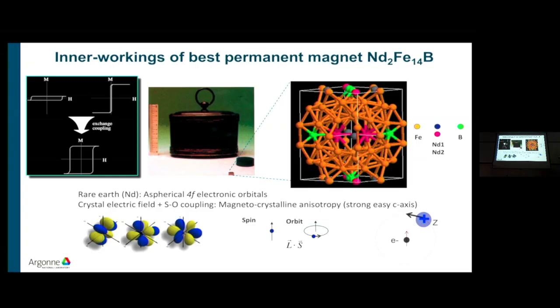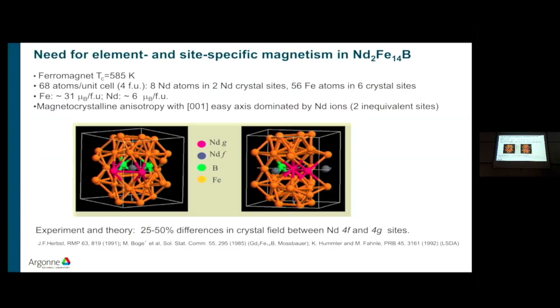And then you need anisotropy or coercivity. You use rare earths because rare earths have anisotropic 4f orbitals. And when you put them in the lattice and in a crystal field, you deform the charge density, so the wave function is anisotropic, and if you add spin-orbit coupling, you can couple the direction of the spin to the crystalline axis. So these neodymium iron boron magnets have a c-axis anisotropy that is dominated by the neodymium ions. Now, when you look at this structure, the ordering temperature is high, which makes it a good magnet even for high temperature applications.